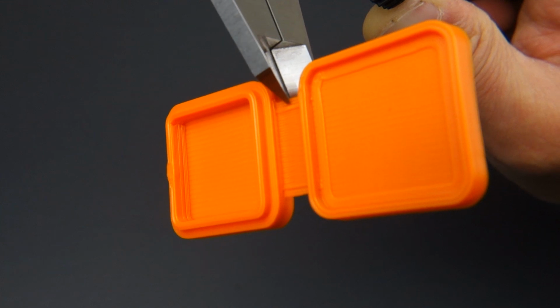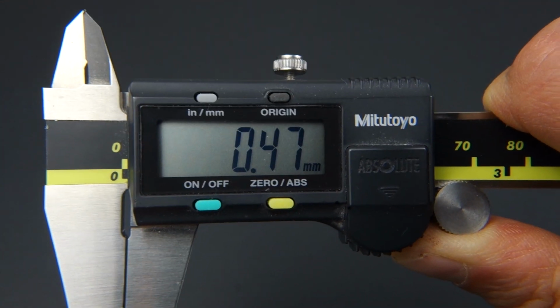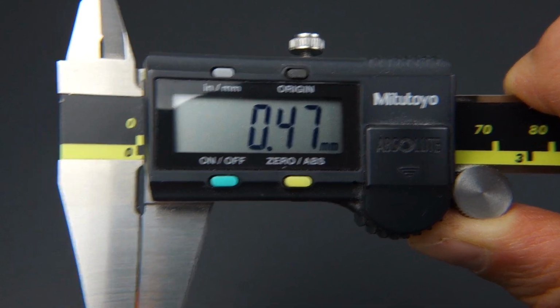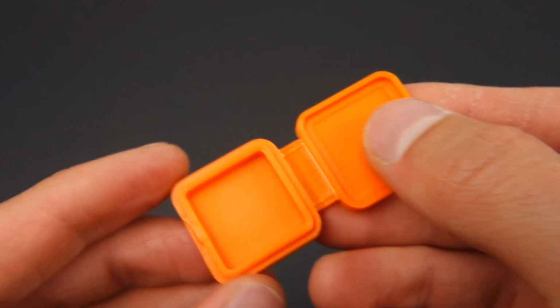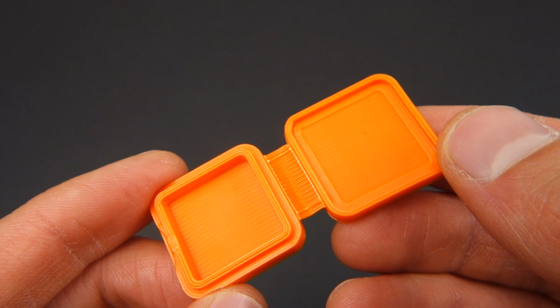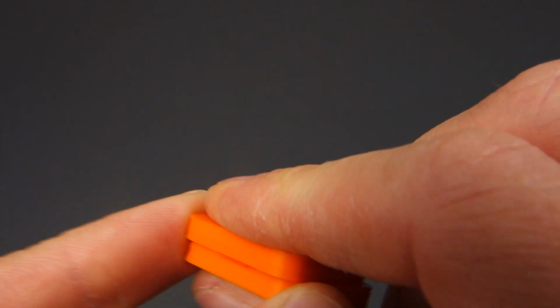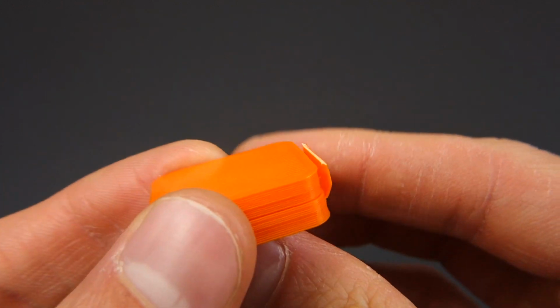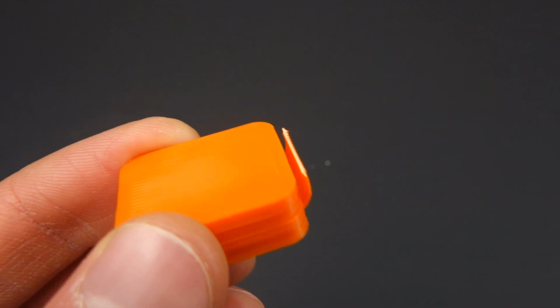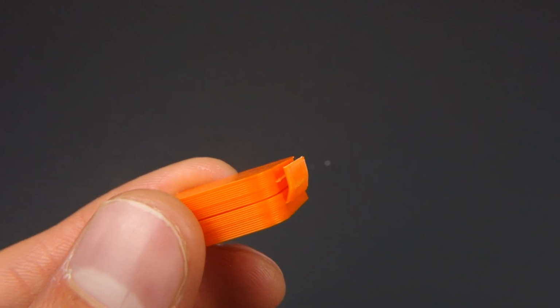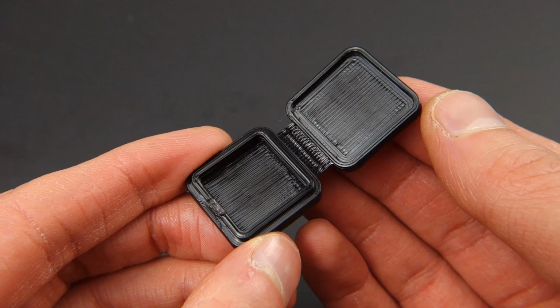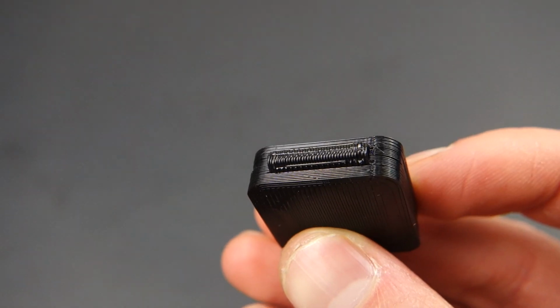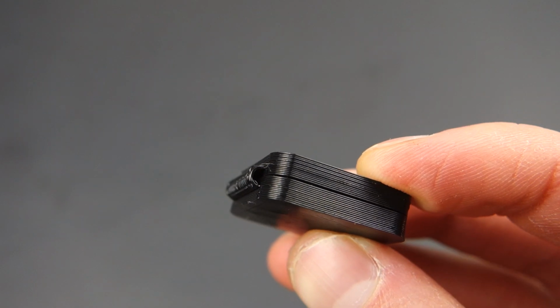So we'll grab our calipers, and unfortunately the hinge thickness is 0.47 millimeters thick, which is significantly more than 0.3 millimeters. But we'll go ahead and test to see how the hinge works. We close the case and snap the hinge again. Unfortunately, tough PLA is still too stiff, even though the hinge bend radius is larger than earlier. And so we'll just switch to Cheetah, and just as expected, the Cheetah hinge is working great.